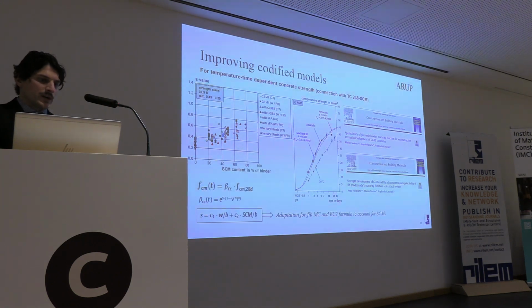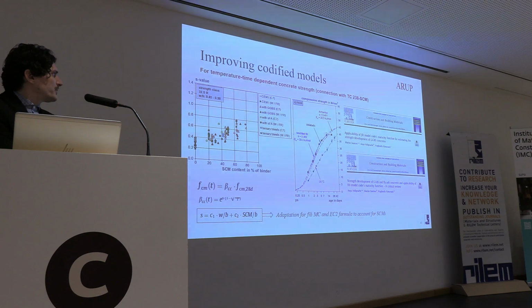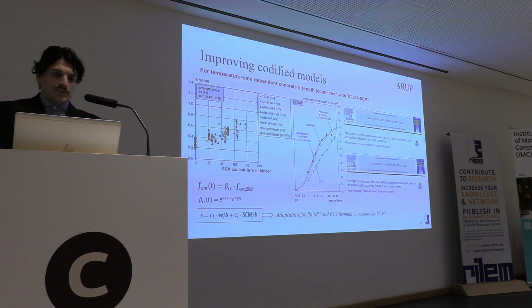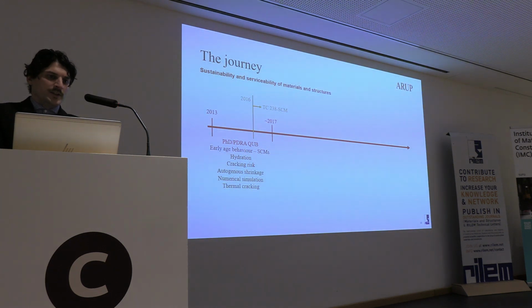So through this work, we were able to refine the models and produce a simplified approach to accounting for supplementary cementitious materials in concrete strength development, also considering temperature and time effects, which resulted in very, very good correlations between strength predictions and actual strengths. And it's actually a simple method that has been adopted quite widely. At least I've talked to some people that have been adopting it. But also was my introduction to TC 254 on cracking in massive concrete structures. And this was quite important.